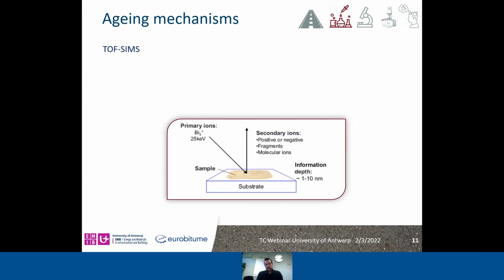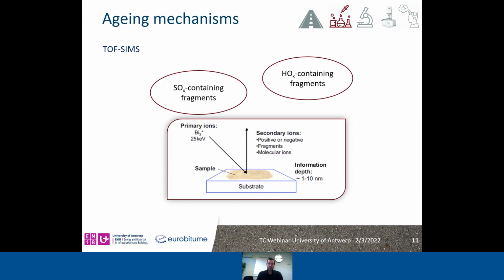Having to some extent support that we have a clear transition from the fast to the slow rate phase around 8 days for these binders, then at this time interval at 8 days, with this thin film oven testing, a TOF-SIMS was used. The principle of this technique is based on the fact that we bombard the bitumen surface with bismuth ions, and the emitted ions, if specifically energetically charged, can give information for different oxygenated products. For example, about sulfoxide-containing fragments that exist before and after aging in the bitumen surface, as well as hydroxyl-containing fragments. Also, other information for polycyclic aromatic hydrocarbons was extracted.